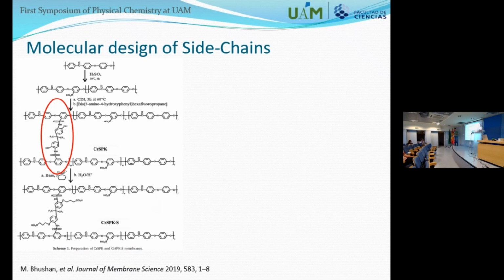But why do they try to do this cross-linking? Because the cross-linking of the polymeric chains helps to reduce the water uptake. When we are cross-linking, we are making a more entangled structure. Since it's more rigid, it will have lower swelling. And then, what we saw, the problem that if the swelling is too much, we have the crossover of the ions and everything. So the cross-linking is very effective for that.